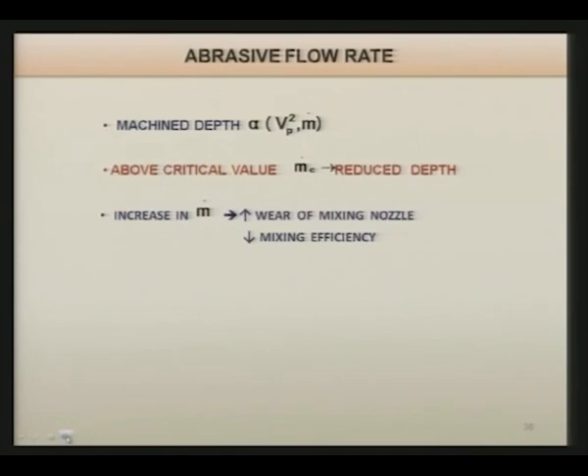Machine depth is proportional to the velocity of the abrasive particles as well as the mass flow rate of the abrasive particles, that we can see here. Above the critical value of the mass flow rate of the abrasive particles, the depth of cut starts reducing. An increase in mass flow rate leads to higher wear of the mixing nozzle and reduced mixing efficiency. That is why there is always an appropriate or critical value of the mass flow rate of the abrasive particle.